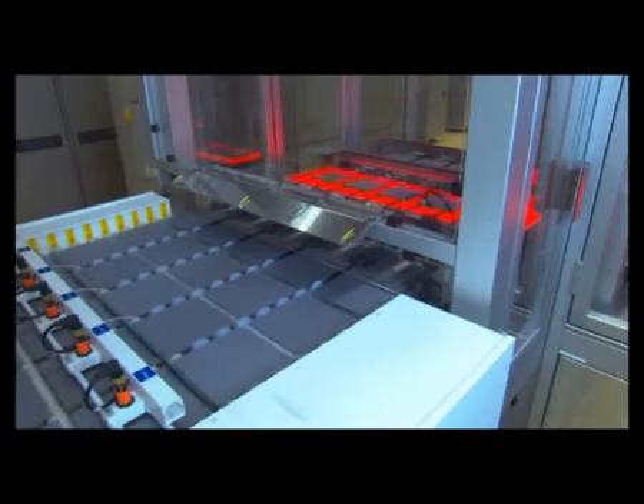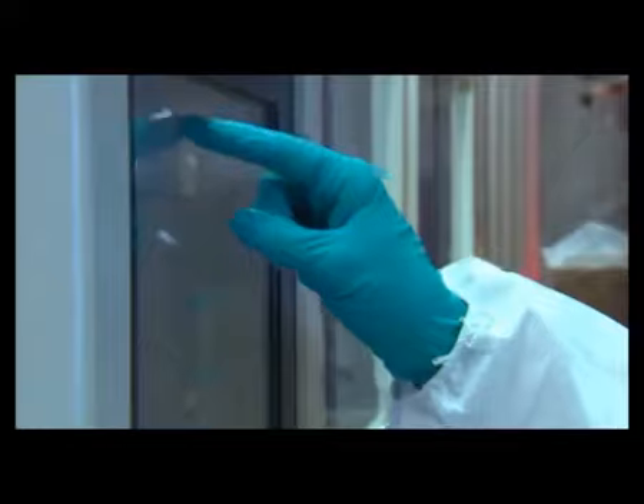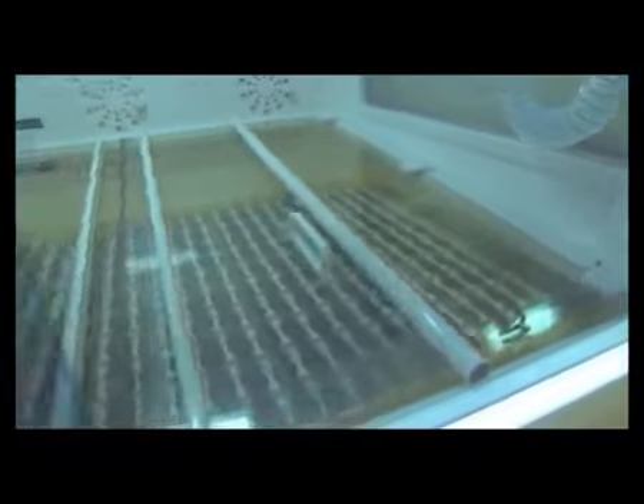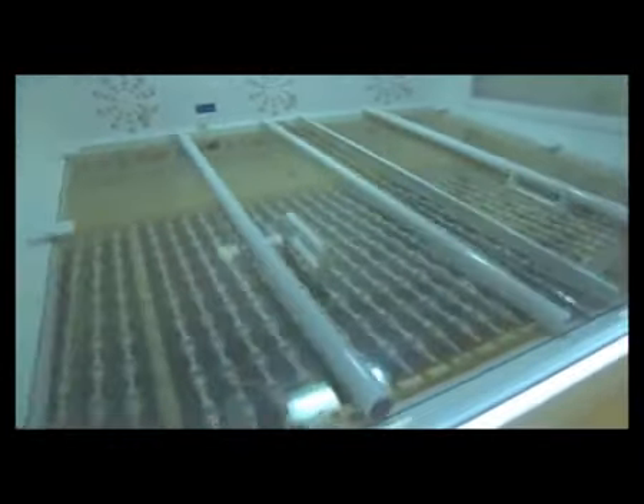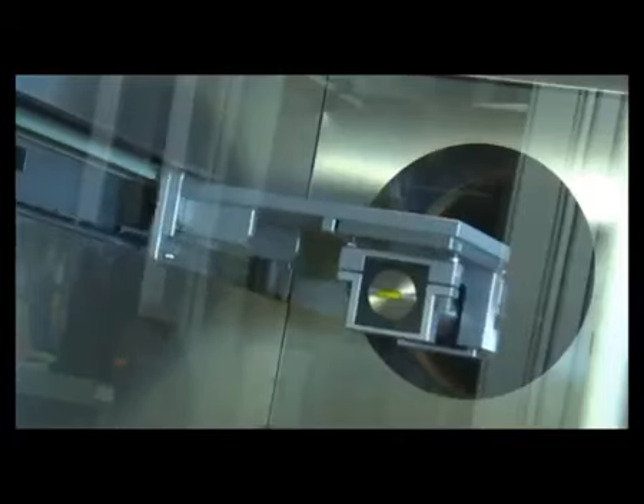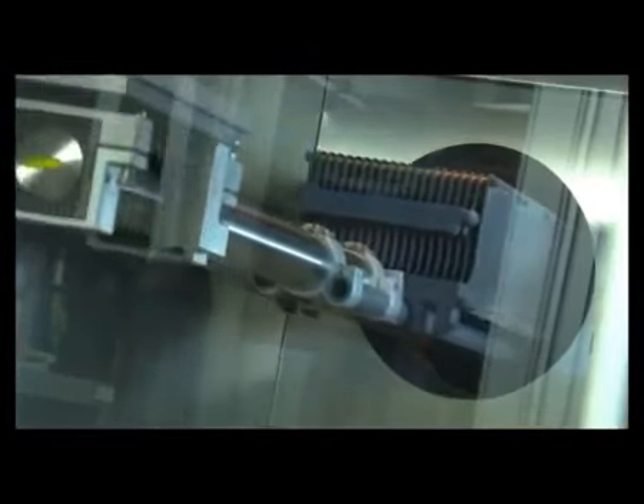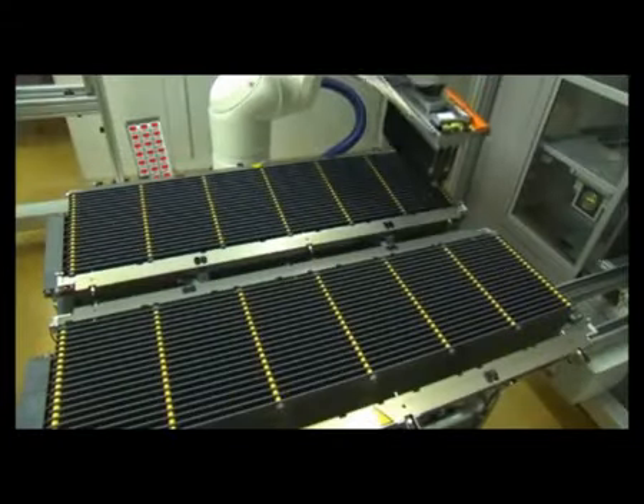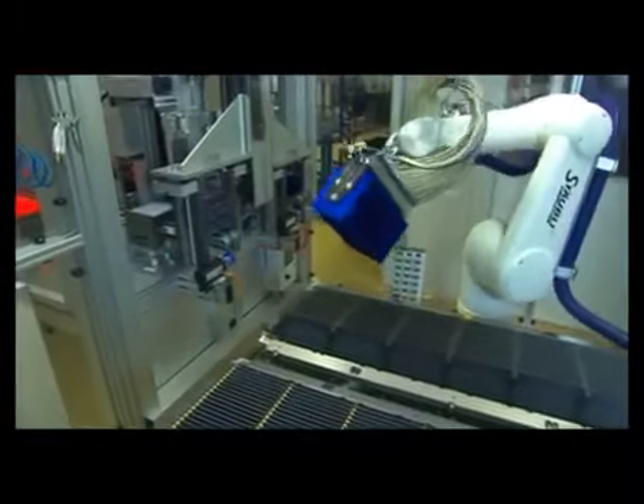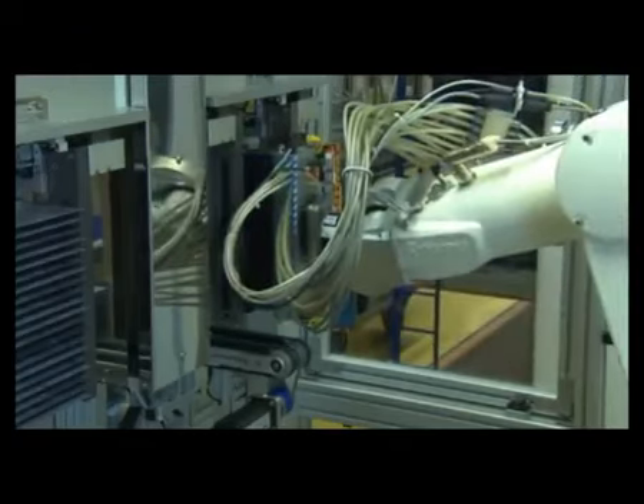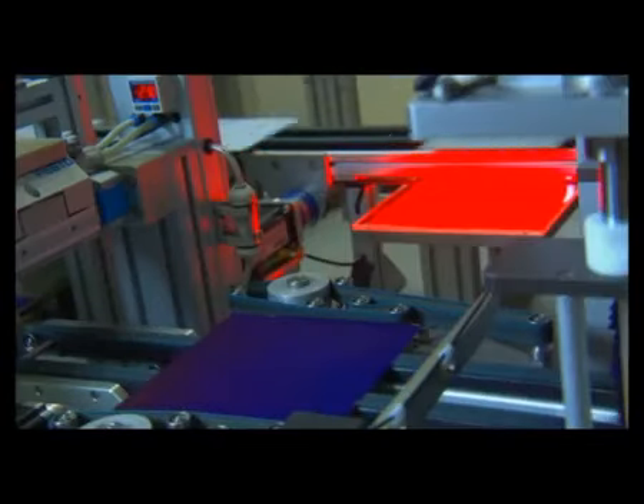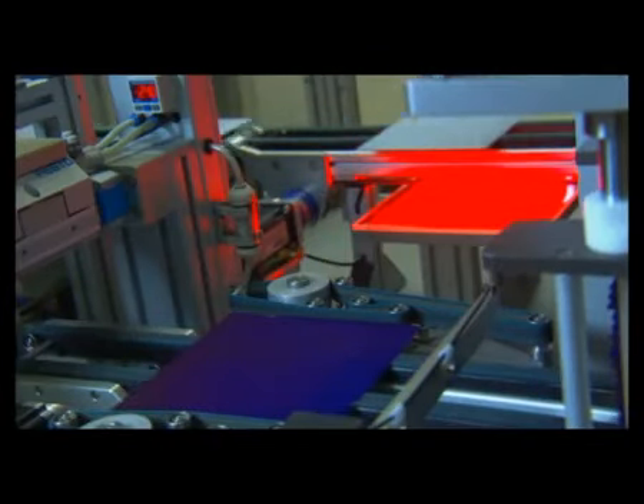Once again, the cells are cleaned and etched under the scrupulous supervision of our staff. The 0.2 mm thin cells are then placed in an acid bath, where only their bottom and edges are exposed to the acid. The effect: the positive side, the bottom, is electrically isolated from the negative side, the top. The solar cells then enter a plasma chamber, where they are given their typical color. The blue surface reduces optical loss by preventing unwanted reflections. As a result, more light can enter the cells, and more power can come out of the cells.